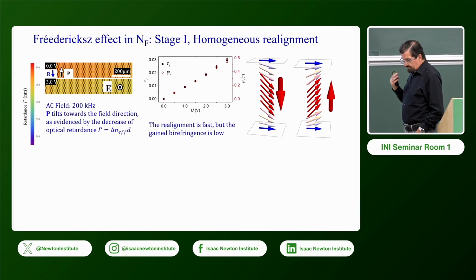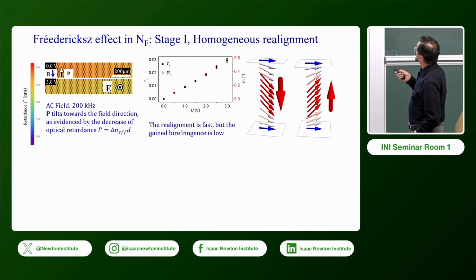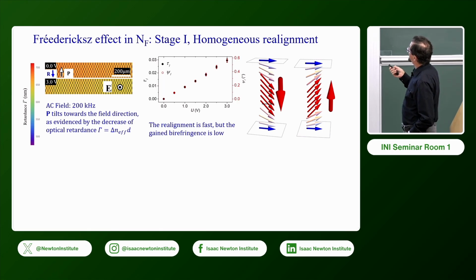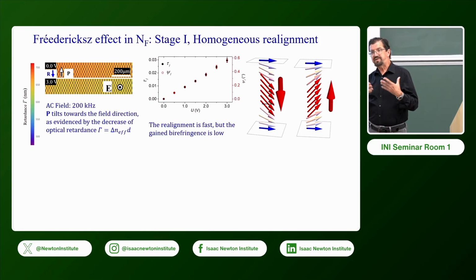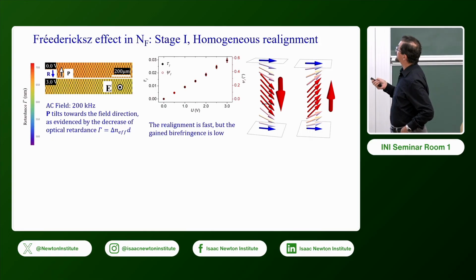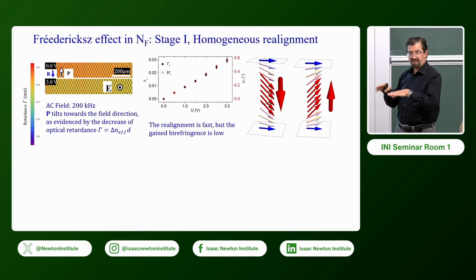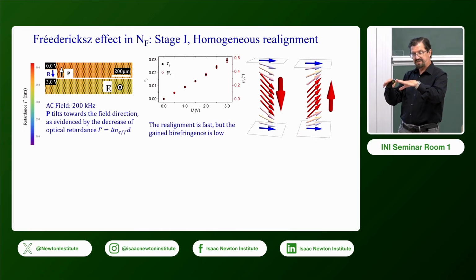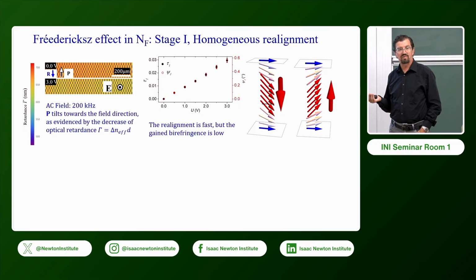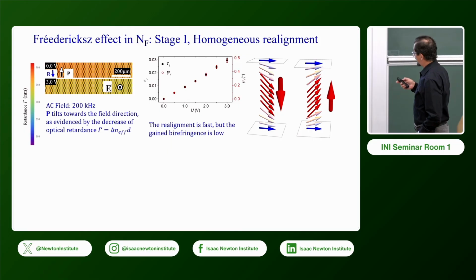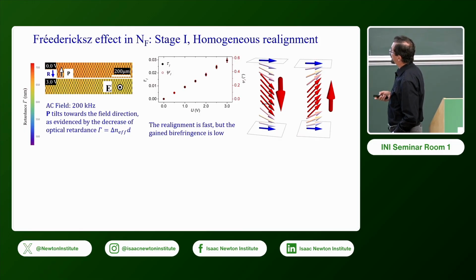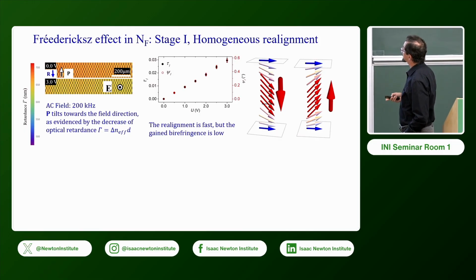So the ferroelectric nematics, unfortunately, if they are in the ferroelectric nematic phase and you apply this electric field up and down, the change in optical retardance is not that high. We recalculated it in terms of the angle of oscillations. It's less than 1 degree. So it's a small quantity. You cannot develop a robust optical response on the basis of these oscillations.